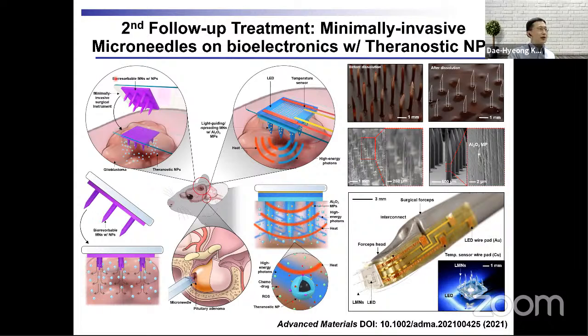In the case of bioresorbable microneedle, it contains theranostic nanoparticles. So it has an iron oxide core for MR imaging, and on the silica shell, we have PDT dye, photodynamic therapy dye, and conjugated chemo drug. And if we can deliver high energy photons like UV light, then the PDT dye will generate ROS, reactive oxygen species, to oxidize the tumor cell. Also, it can release the chemo drug for chemotherapy.